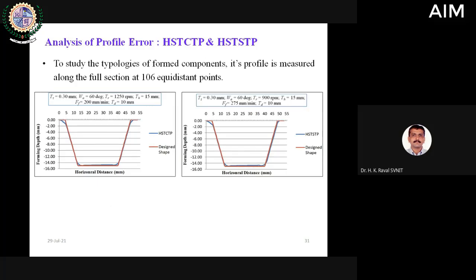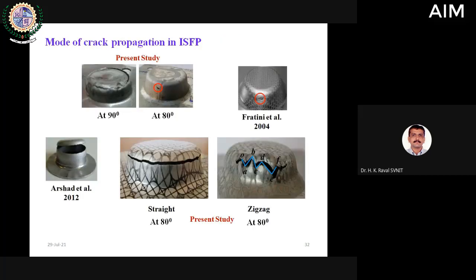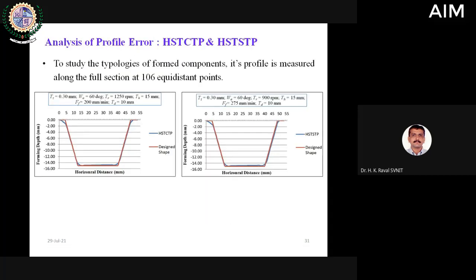And the shape formed after forming is also shown here. It is quite a good match, if one can see, except close to the flange. Close to the flange there is a deviation, so that is another aspect to be controlled. But otherwise, right from the -2 depth till its full depth, the shape of the cup is very close to the target shape. So that is the result. One can control the spring back or geometric accuracy by varying the parameters.